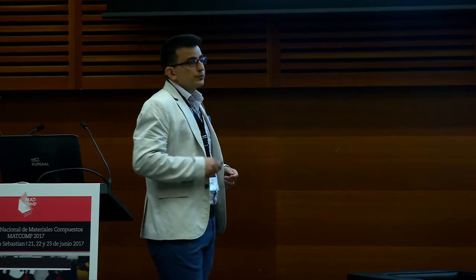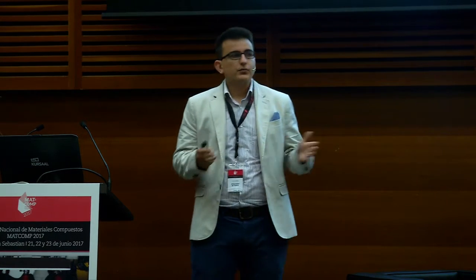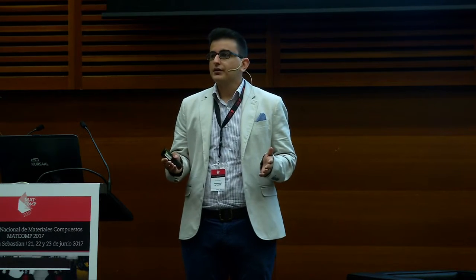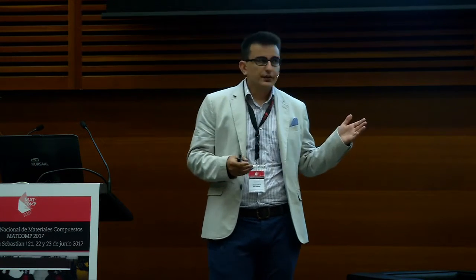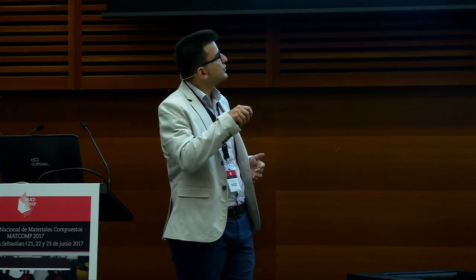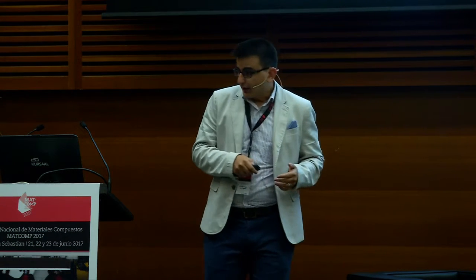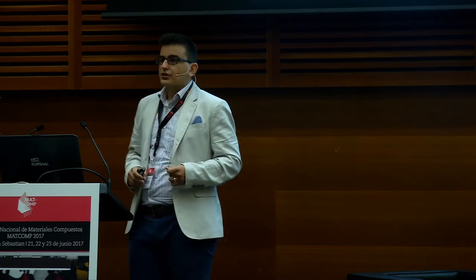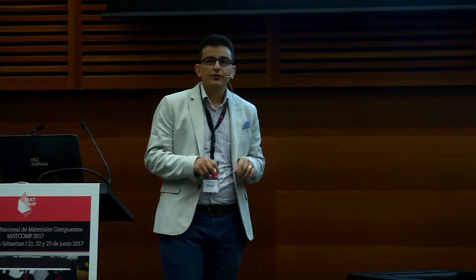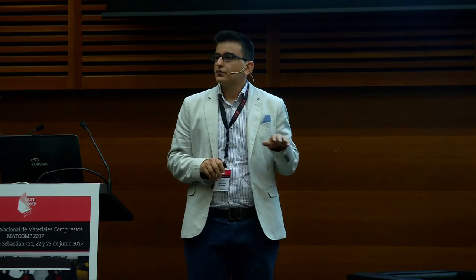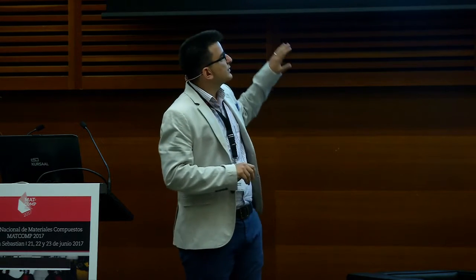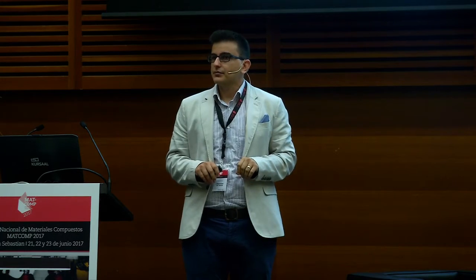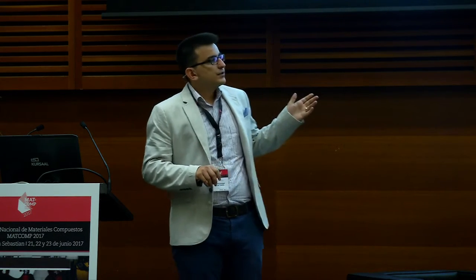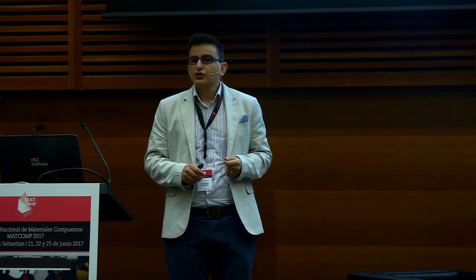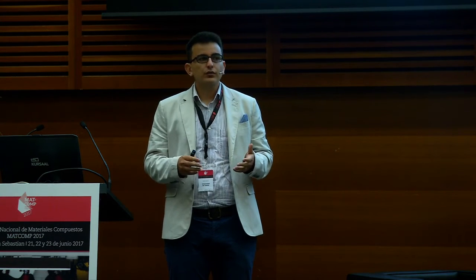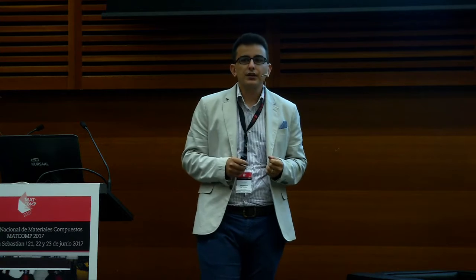And here is the fracture zone. On the other hand, some of the specimens failed in shear mode exactly at the matrix crack region, where we have 520 Newton force at fracture. So it's clear that there's a 25% reduction in force at fracture having the same type of defects in the specimen. So this is a coupon level which we can control as much as details we can.